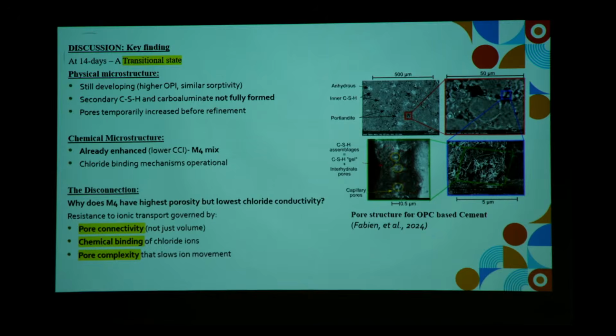However, what we do see is that the physical microstructure, as I said, is at a transitional state. It is developing in terms of OPI and similarly with the sorptivity. However, with the chemical microstructure, we are already seeing the benefits of introducing our LC3 in our mixes, with the chloride binding mechanism against our chloride ingress.